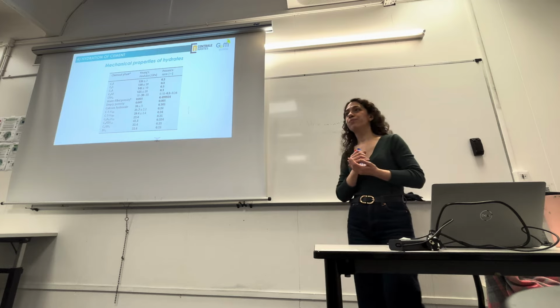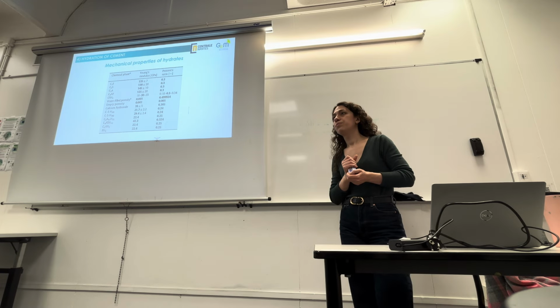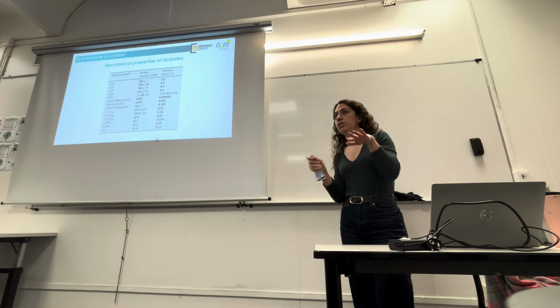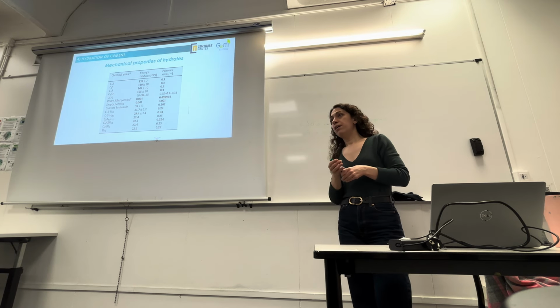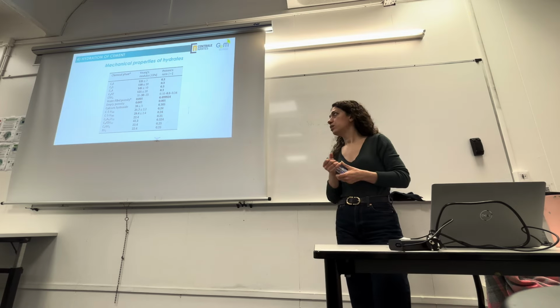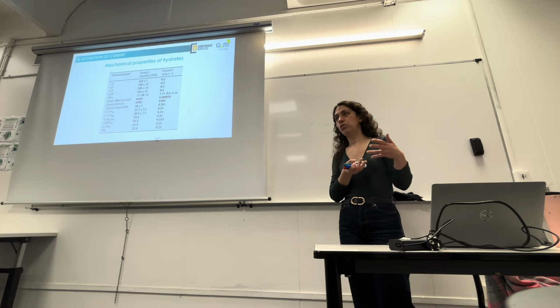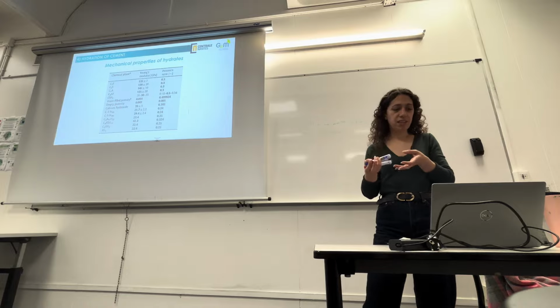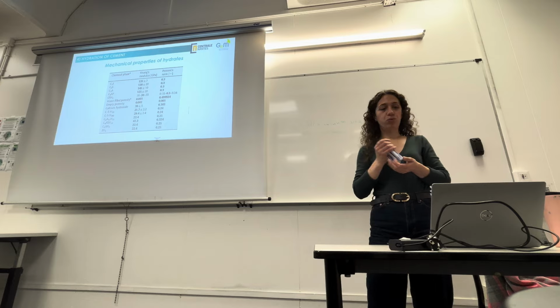Okay, so if you add water to the concrete, it will dissolve Portlandite until the pH of the water is high enough, and then the Portlandite won't dissolve. Yes. Once the pH is right again, Portlandite will stop dissolving. And if you dissolve all the Portlandite and still the pH is too low, you will start to dissolve the other hydrates of the cement paste, and especially the CSH will also start to dissolve. But before dissolving the main part, that is the CSH, the Portlandite will dissolve first in order to increase the pH.